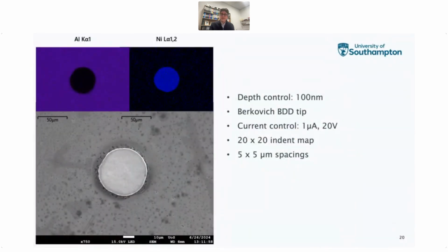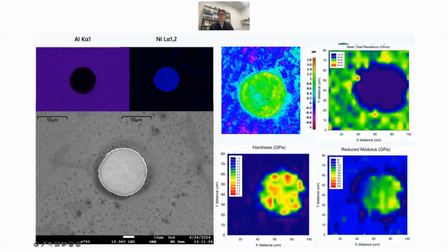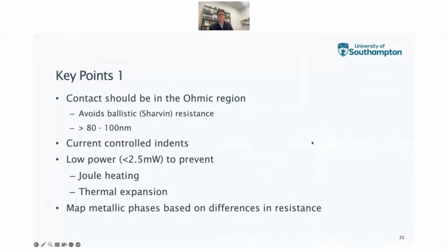Once you've taken account of that, you can start to think about how you might go about looking at this correlation of the phase spatially, which we're interested in. You can see one of the intermetallic particles here, and we've done a 20 by 20 indent map on this at 5 by 5 micron spacing, using 1 microamp and 20 volts floating with the Berkovich tip and a penetration depth of 100 nanometers. And then we can start to get correlation between the surface height topography, the differences in the hardness and the reduced modulus, and indeed the differences you might see in the total mean resistance.